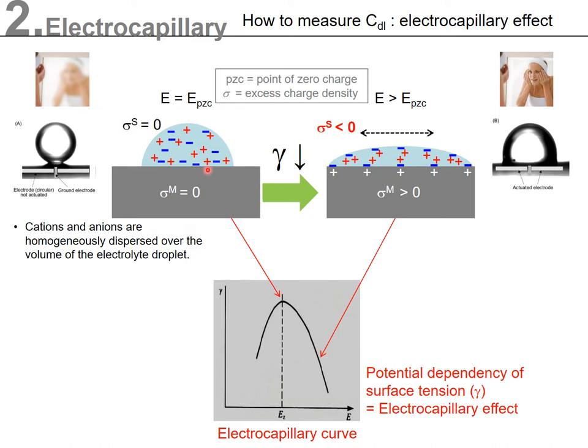So let me focus on the interface between the electrode and electrolyte. You have 1, 2, 3, 4, 4 positive ions, and also 1, 2, 3, 4, 4 negative ions. So the net charge at the interface would be zero. So at the point of zero charge, I can say the excess charge density of metal and also excess charge density of solution, in this case electrolyte, should be zero. At the point of zero charge, cations plus here and anions minus here are homogeneously dispersed over the volume of the electrolyte droplet. Then the shape of the droplet looks like a hemisphere. Or if your liquid has very high surface tension, then sometimes your droplet looks like just a sphere.